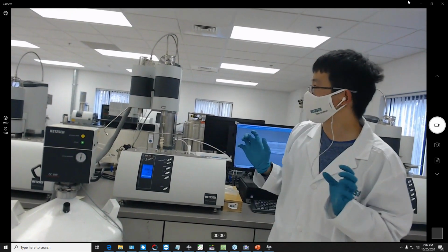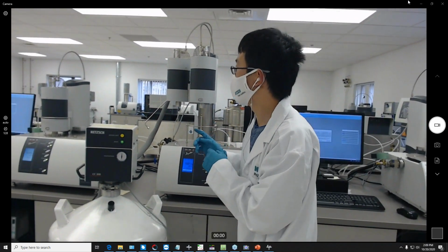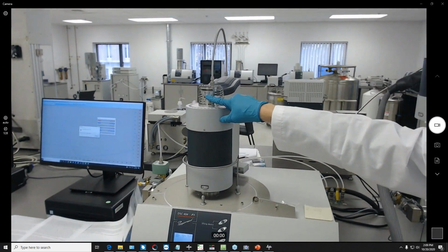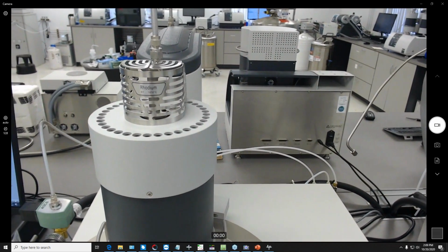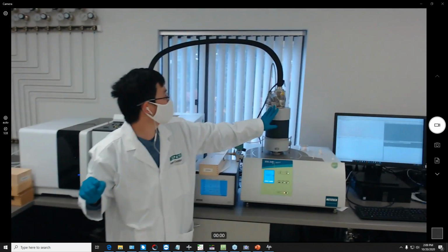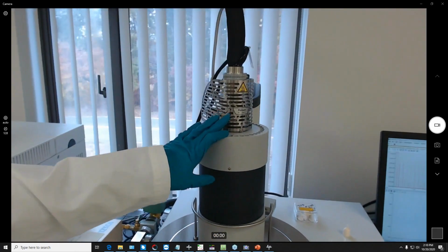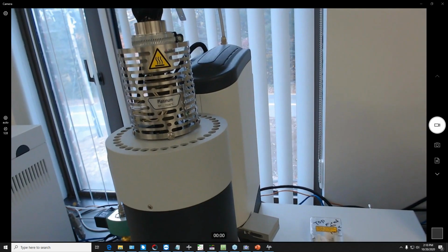Now we have a couple other furnaces here in our lab. So here on my left is a rhodium furnace. So this one can go from room temperature to 1650 degrees Celsius. And then here I have a platinum furnace, which can go from room temperature to 1500 Celsius.